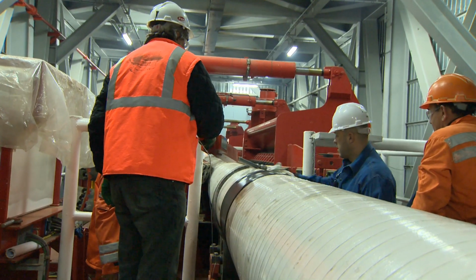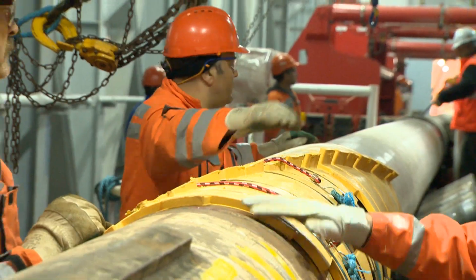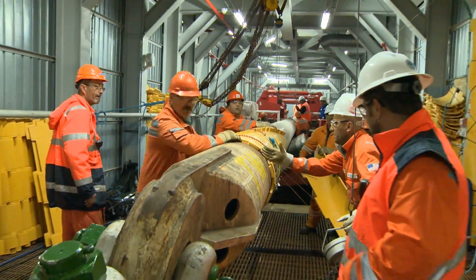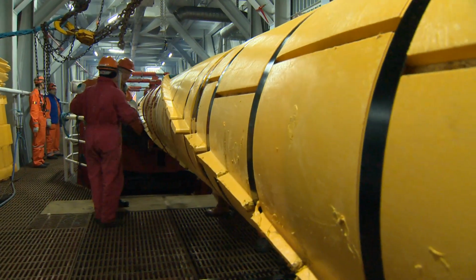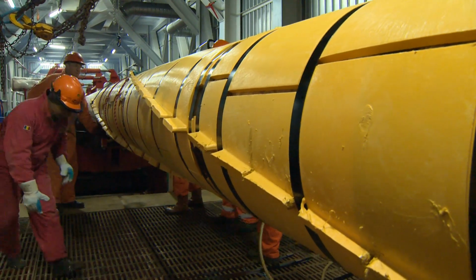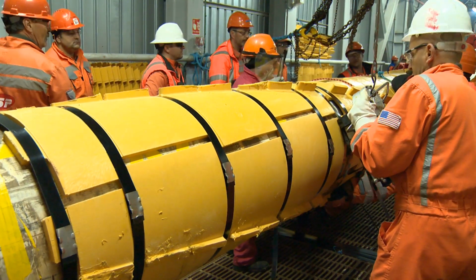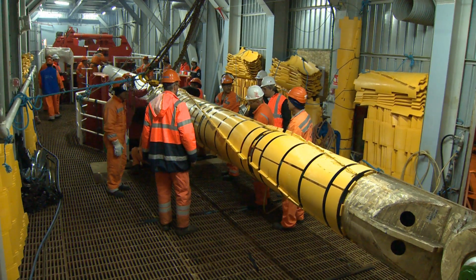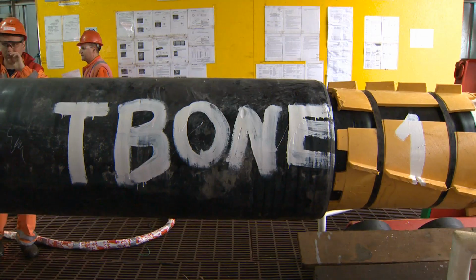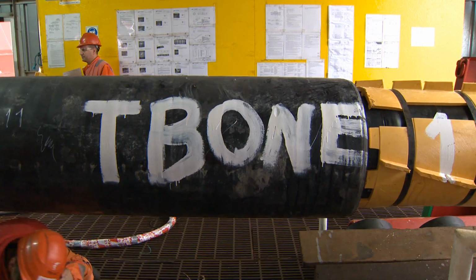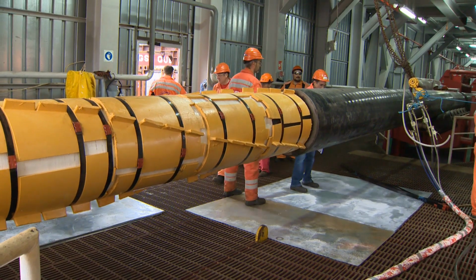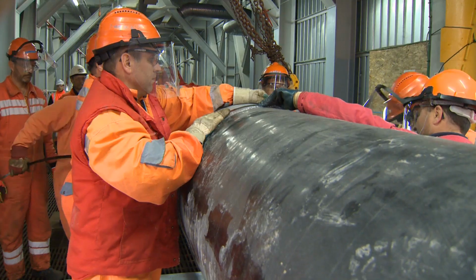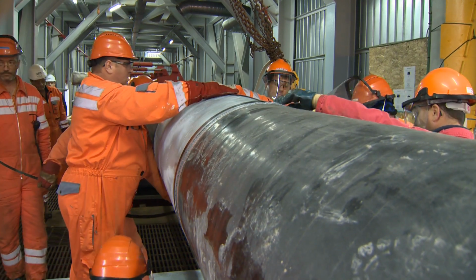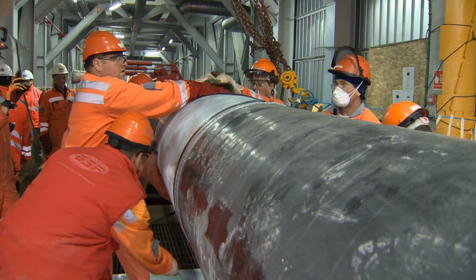It is obviously a little bit crowded at workstation 6, but there are 2 more operations carried out here. Firstly, the pipe that goes into the mounting casing is wrapped in staves, or as everyone calls them, crocodile tails. This is for obvious reasons. And secondly, for the concrete coated pipe, due to the fact that the cement filled joint coating is thick, the protection area had to have the same thickness. This is done with foam injection.